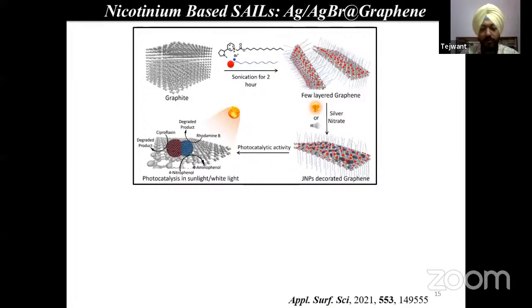Then we thought, why not use these surface active ionic liquids for exfoliation of graphene from graphite. So one can see over there the three-dimensional structure of graphite. We have bath sonicated the graphite in the presence of nicotinium based ionic liquid for 2 hours to get few layered thick graphene. You can see there, few layered thick graphene.